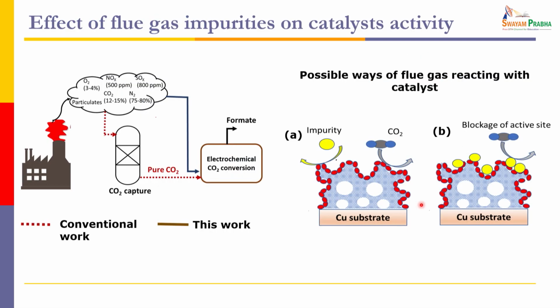One other thing we have also done is this: if you look at industrial gas, you will not have pure CO2. If you look at the coal industry or any power plant, not just CO2 will come, you will have SOx, NOx and so on. Other impurities will always be present along with the CO2. To mimic that, we deliberately mixed SOx and NOx with CO2 and then did an experiment, just to mimic the industrial condition. We chose about 500 ppm of NOx and 800 ppm of SOx mixed along with carbon dioxide, purged it into the solution, and then did the experiments.